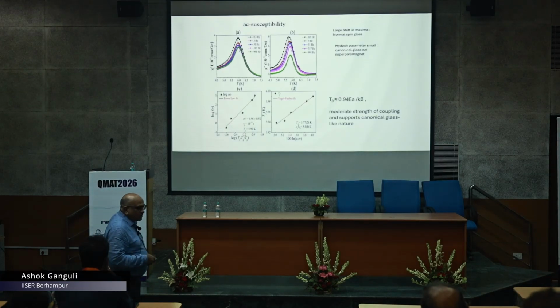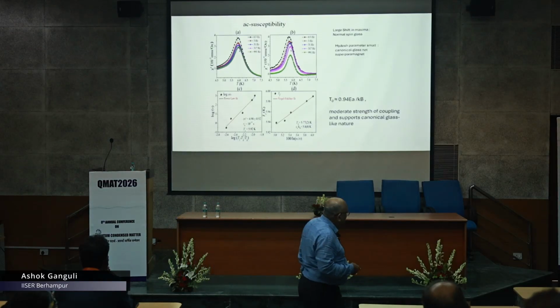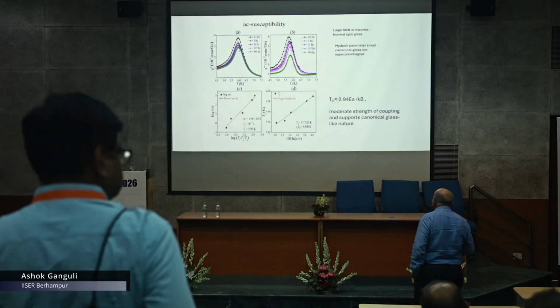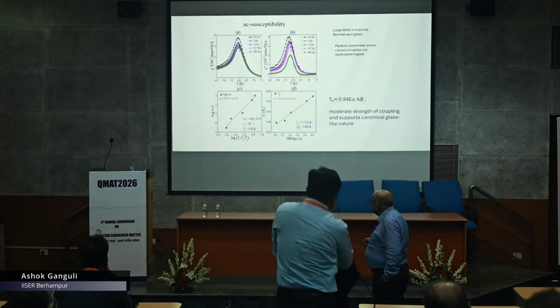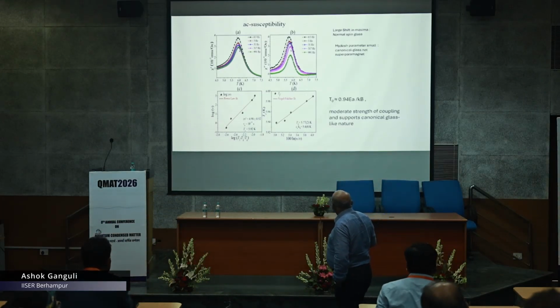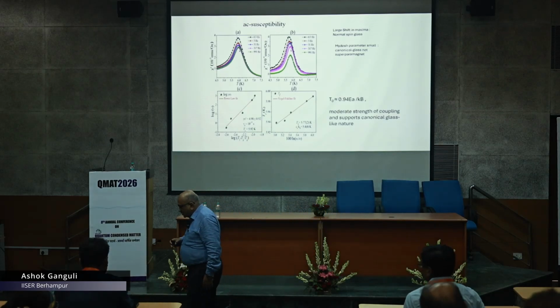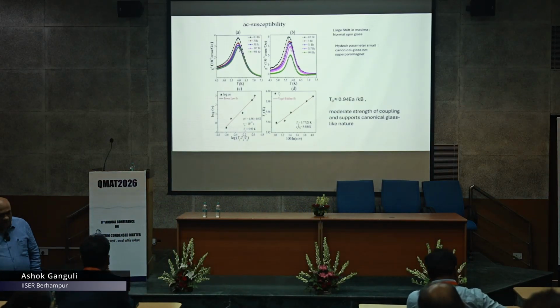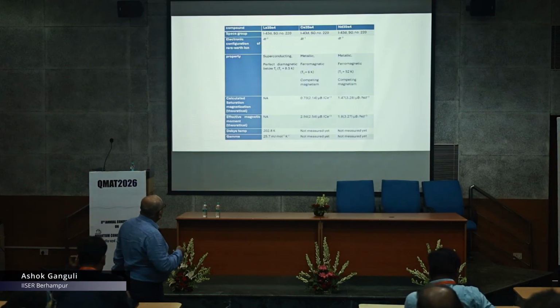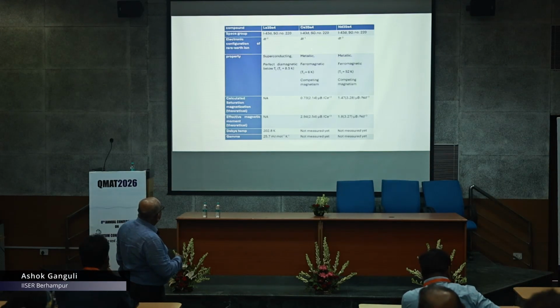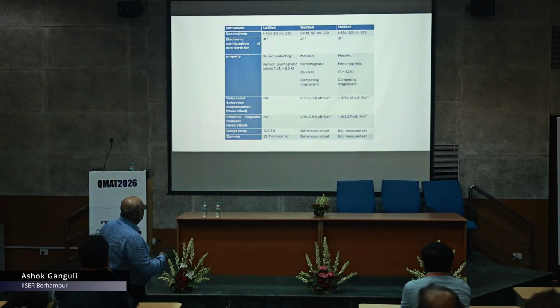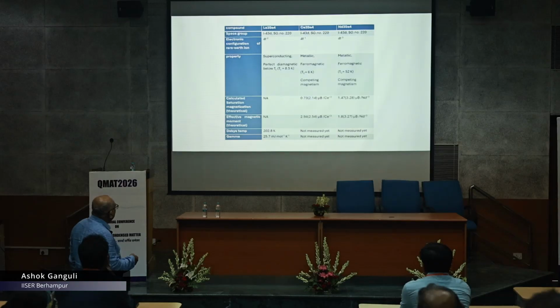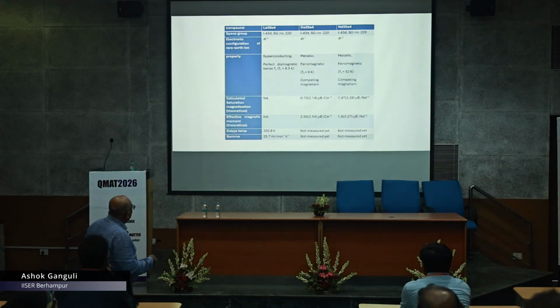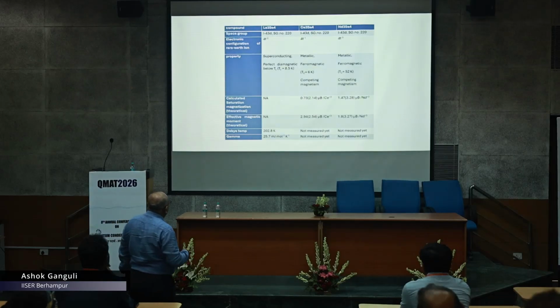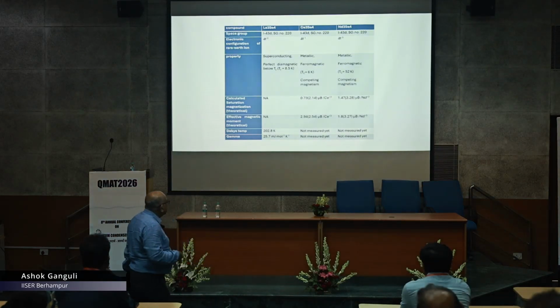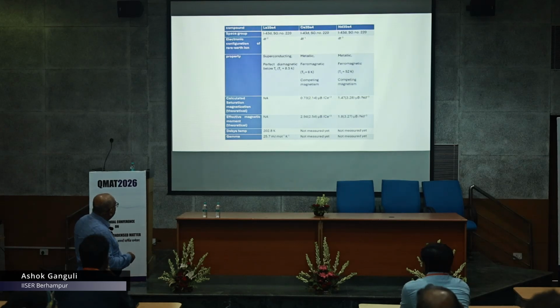And we also looked at the spin glass type of behavior, looking at the variation of the AC susceptibility, and getting numbers using the power law fit and the Vogel-Fulcher fit, which kind of explain whether you have the canonical spin glass or the cluster glass. So in this system, if you want a comparison of these chalcogenides which are non-layered, you can have superconducting, metallic, and itinerant ferromagnets, with different TCs showing competing magnetism, and some of the properties we are trying to measure of some of these phases. But all of these papers are published.